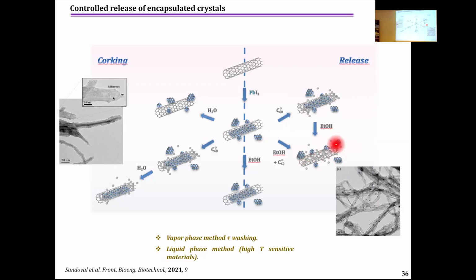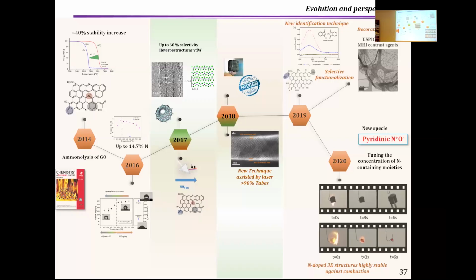In this approach, we were able to remove almost all the material from the sample. However, when we encapsulate this material and afterwards use water as solvent, the lead iodide remains inside the nanotube. So this strategy can be used for corking or release of the material inside. We can take advantage of these approaches in order to selectively modulate the material contained inside the nanotubes. So this is more or less an overview of the evolution of these techniques we have developed.